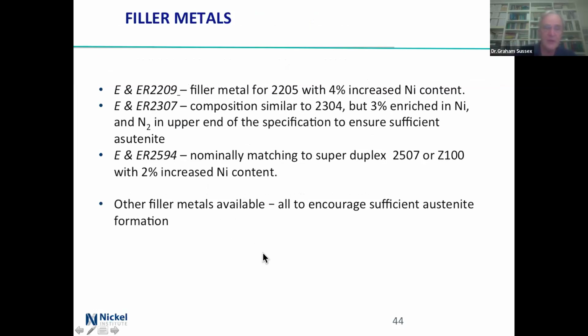Filler metals, E or ER, so electrodes or rods. Filler for 2205 has about 4% over in nickel. 2307 is very similar to 2304, but about 3% enriched with nickel. And make sure that you've got the upper end of the nitrogen to get enough austenite, because you can't put too much nickel in there, otherwise you'll move up into the next range.